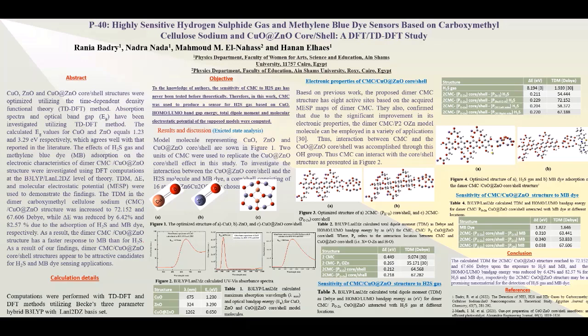Thus, in this study, time-dependent density functional theory calculations were carried out for the optimization of copper oxide, zinc oxide, and copper oxide zinc oxide core shell structures. The major aim of our study is to enhance the sensitivity of copper oxide and zinc oxide by making a core shell structure, and to study the sensitivity of CMC copper oxide zinc oxide core shell to H2S gas and to methylene blue dye. Figure 1 shows the optimized structures of copper oxide, zinc oxide, and the core shell structure.